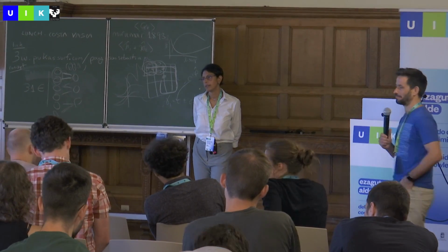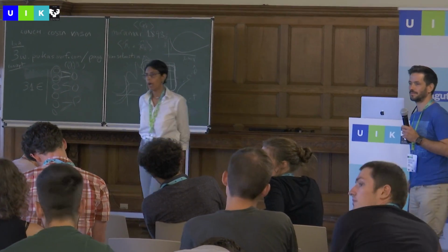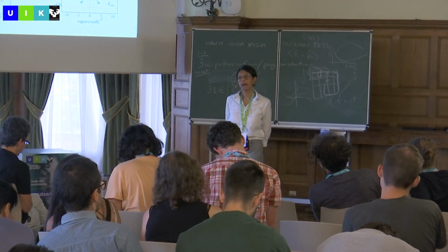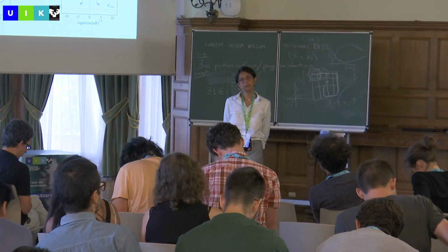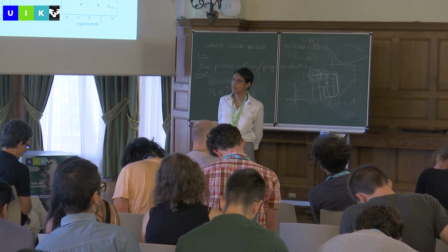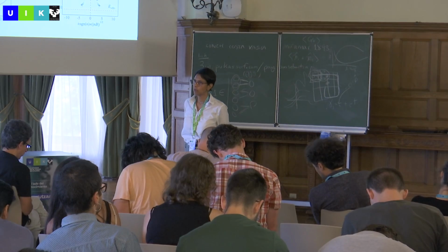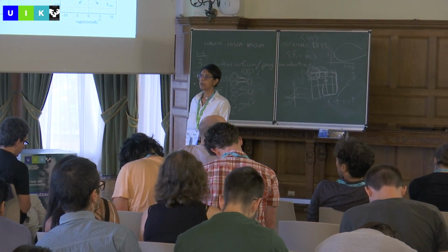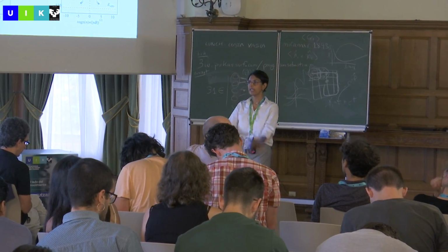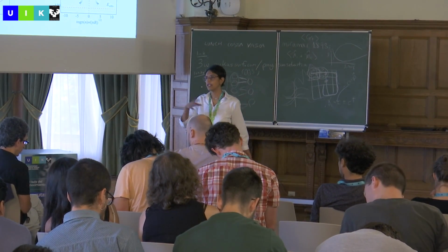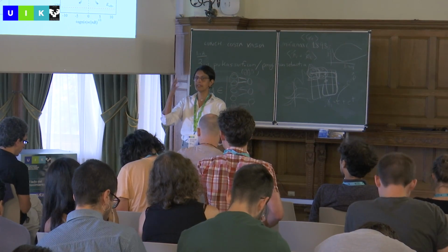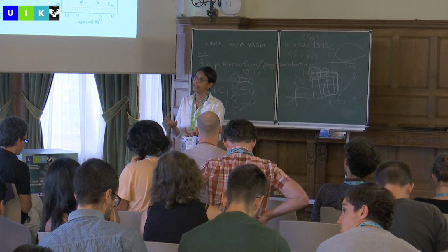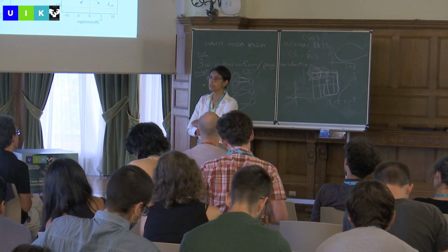Okay. You mean above the gap energy? Yeah. If the gap is that big for some reason, even if you bias above the gap, we still are not able to. This is the charging problem. For some reason, in these insulators, the electrons don't leave the vicinity immediately, and then they charge up that local area. So essentially, we're not able to tunnel anymore, and we basically just crash into the sample.